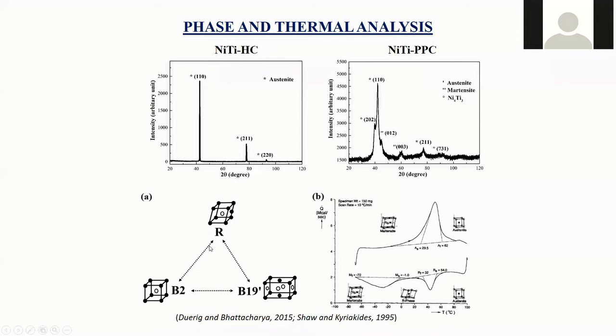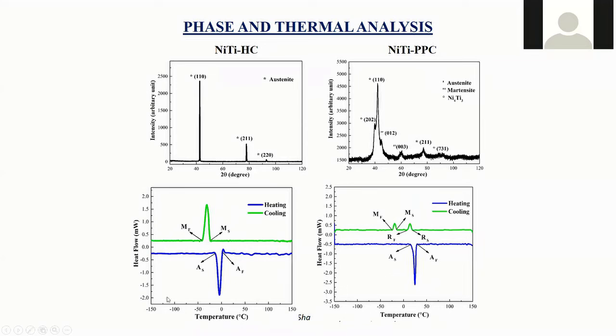Now, R phase is another unstable product phase, which has a rhombohedral shape. So this austenite phase converts to R phase, and that finally converts to the martensite phase. So there is a two-step conversion happening. This is what is seen from the DSC thermograms itself.